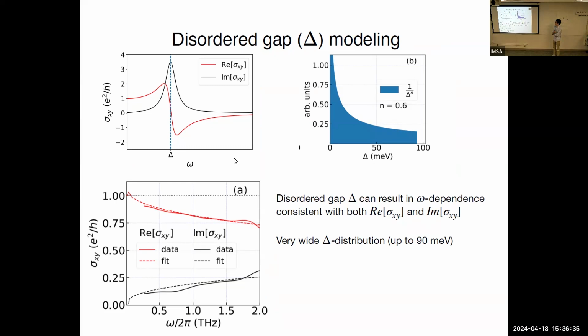We come up with a distribution of the gaps, and it turns out it can explain all of the subtleties of our data, why it's not quantized, and also why it has this frequency dependence. Mostly that's the reason why it's hard to get a quantized response in anything but the DC limit, because you have this very large gap distribution, which I think would be addressed in the near future by chemists who maybe will come up with a better way of doping the samples with chromium or other ferromagnets.